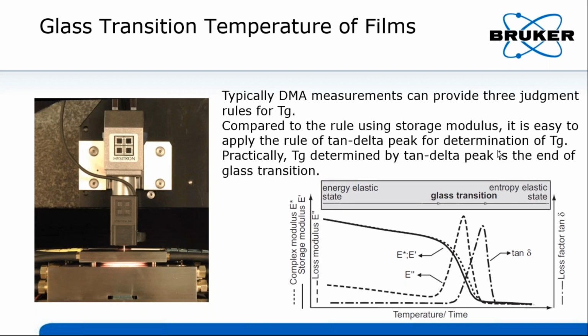Tg. One point that needs to be emphasized here is that glass transition is actually a band of temperature, not really a temperature point. And the DMA measurements provide an advantage of three observations for glass transition. We can see the storage modulus onset suggests the beginning of the glass transition, and the loss modulus peak happens at the middle of glass transition. Finally, the tan delta peak is the end of the glass transition. Therefore, using DMA at different temperature levels, we can get the full information of glass transition.